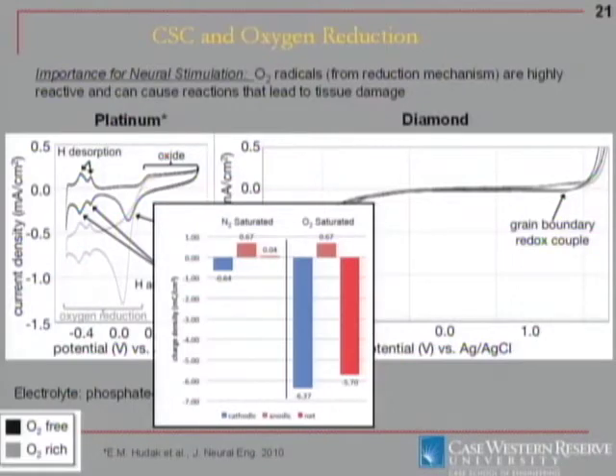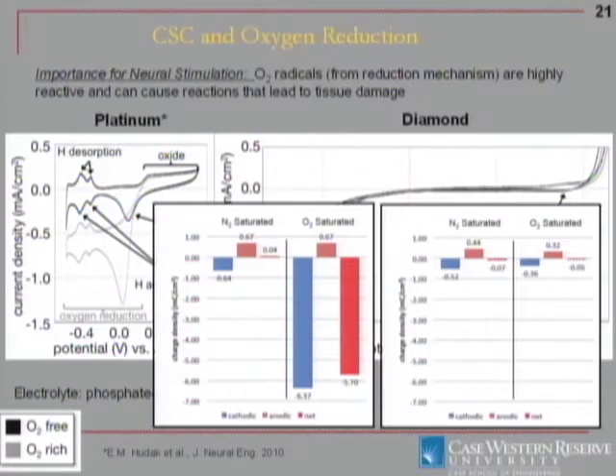Of course, that's not the way tissue is. Tissue has some oxygen present. This is the extreme case of saturating it with oxygen, which of course is much more oxygen than is in tissue. But in that case, you see the significant cathodic reaction of oxygen reduction here. The anodic situation doesn't really change much, so the net amount of current is very negative. So the total amount of charge transfer here is quite irreversible. In diamond, it doesn't seem to matter if the oxygen is there. The currents are actually in the same order of magnitude as the platinum. The net amount is low, so it's very high reversibility. And again, the same is for oxygen.